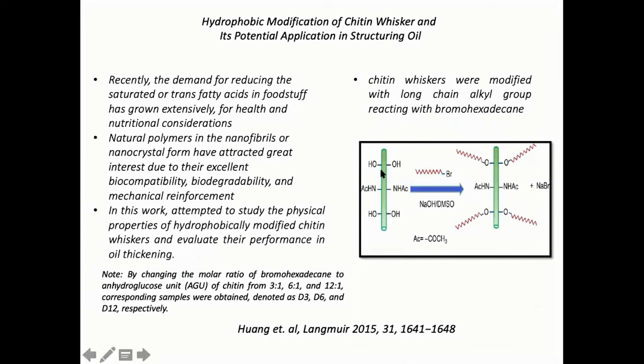Look at this, this is the nanochitin extracted from the crab shell. Simple acid washing, like in the case of nanocellulose. And this is highly hydrophilic. You can see hydroxyl groups. But if you do a small chemistry, reacting with bromohexadecane, you know what you get? You can introduce a lot of alkyl groups. These are all alkyl groups.